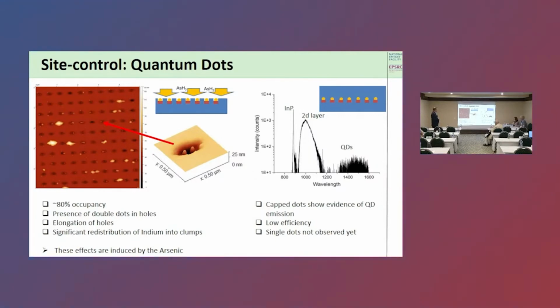We also get quite a lot of clumping, so this actually tells us that in between the holes, even though we can't see it very well in AFM, we do seem to have quite a lot of indium. And when you apply the arsenic, the indium moves around, so that allows us to get site control of dots, but it also causes quite a lot of clumping of indium. So we are still in the process of optimizing this, and I think we just need to reduce the amount of indium. That may also control how many dots that we have in the site control.